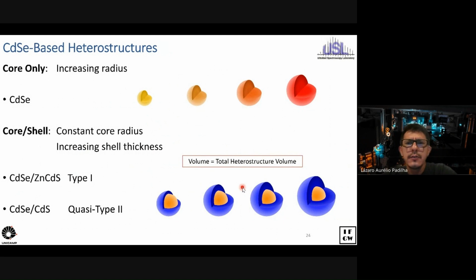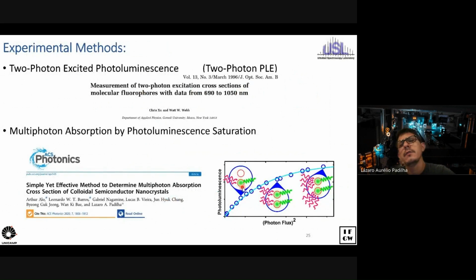So to do this, we have studied a series of core-only and core-shell nanomaterials, and we wanted to get a very precise, very accurate volume dependence. The most used technique is two-photon excited photoluminescence, which is a very awesome technique. However, you have to measure a lot of stuff. You have to measure the linear absorption cross section for the sample and for the reference. You have to measure concentration for the sample and for the reference. You have to measure quantum yield for the sample and for the reference. You have to account for the inner filter effect for the sample and for the reference. And all this introduces error in your experiments.